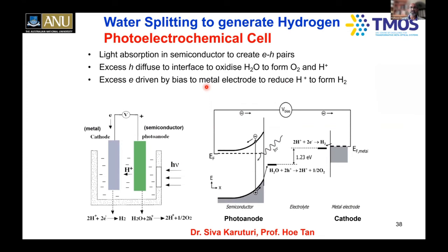We've also been using these nanostructures for photoelectrochemical water splitting to generate hydrogen. This work has been led by my colleagues listed here. We take photoanodes, typically a semiconductor, and excite them with solar light to generate electron hole pairs. Holes come and oxidize water. Electrons go there and react with protons and generate hydrogen here and oxygen here, for example. Okay? It's a simple photoelectrochemical process.